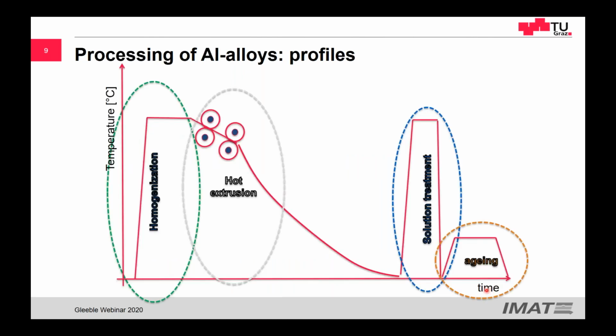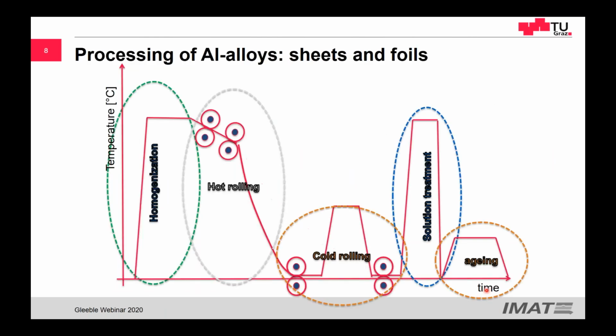It says, is the heat treatment between two cold rolling stages intentional, or is it just adiabatic heating due to the cold rolling? The cold rolling, okay, this is the other one. So this can be done or not. Usually when we do cold rolling at the industry, you start getting material that becomes very brittle and not deformable because of the strain hardening. So the amount of dislocation is such large that we cannot deform it further. So there are in some processes a step that is called the recrystallization step. And with this, we make a thin layer, as thin as possible. We do the recrystallization step. We recover the ductility of the material. We lose the strain hardening of the material. And with this, we can go on further making thinner foils. So this is intentionally when it's done, of course.